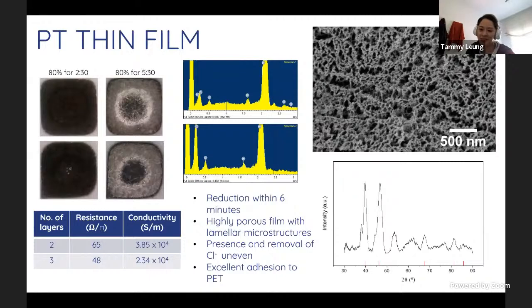Again, another verification that we always do is using XRD to see the purity of the platinum film that was created. And we see here that there are decently matching peaks. However, there are other peaks that we have yet to explain, but again, some of them are attributed to the PET substrate below.